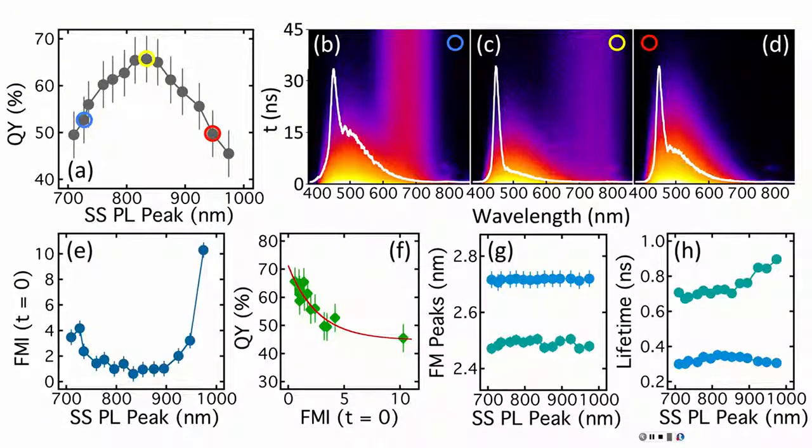So then it probably needs to be addressed also, to have something to explain this. Whatever the origin of this, why is it not changing with size? And if it's gamma-gamma, its intensity is changing, just not its position. The intensity might be just because there's more surface, more contribution of such states. Well, that's how I would interpret it, because it gets big as you get smaller, which just means the surface is becoming more important.